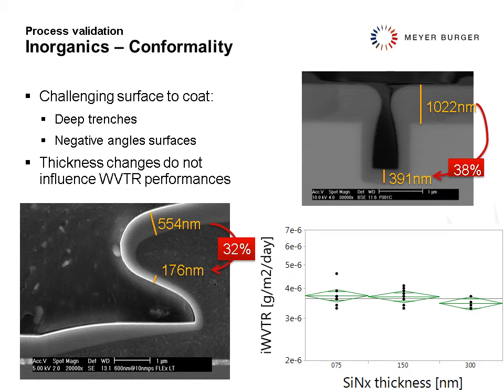Another important thing about inorganics is the conformality. It's very challenging to coat surfaces which present deep trenches, so micrometer trenches or more, or negative surface angles, like in these two cases where you see an explicitly performed trench, or here a negative angle, a feature that needs to be coated. What you see here in white is silicon nitride. And you see that it's possible to have this coating everywhere, but the thickness will not be exactly the same everywhere. So we can coat, but it cannot coat uniformly everywhere.